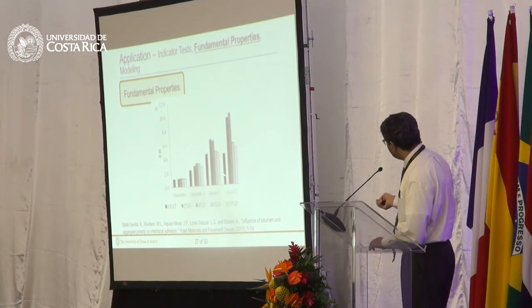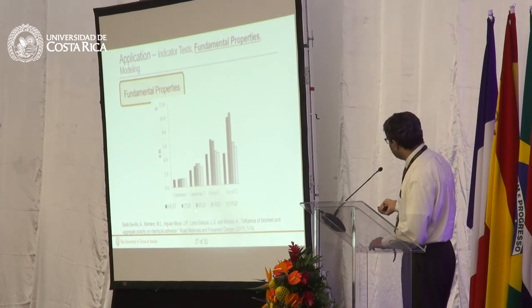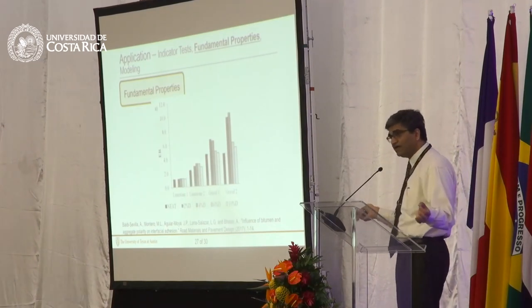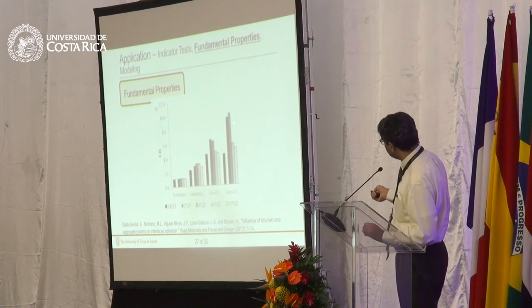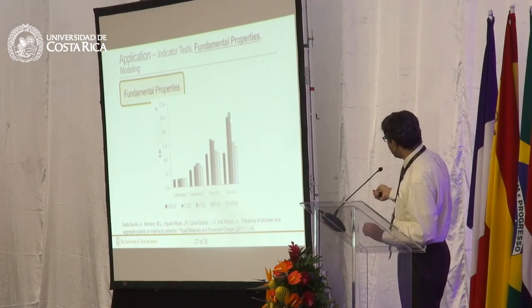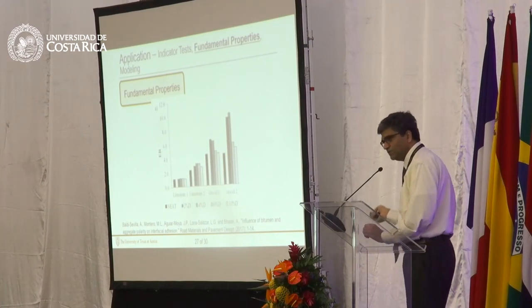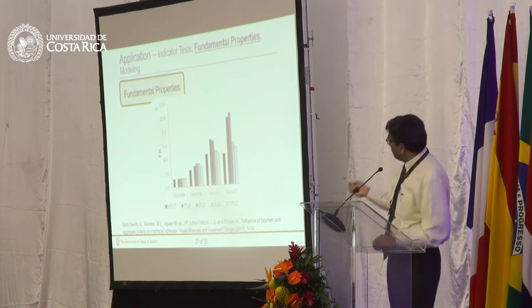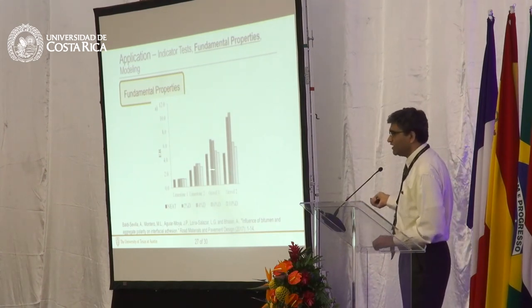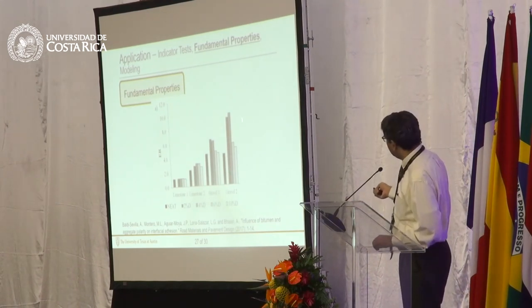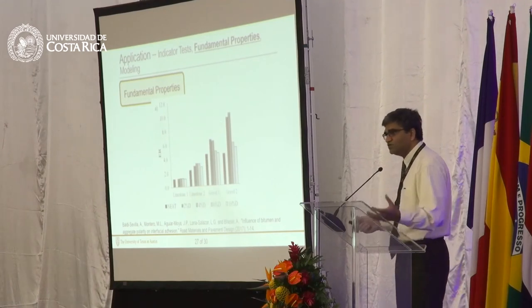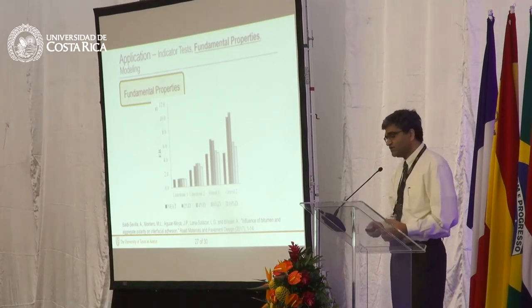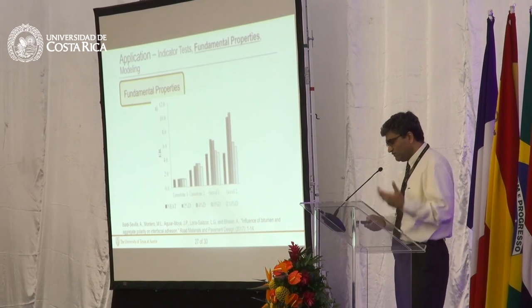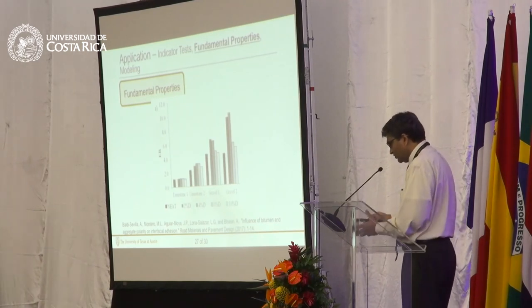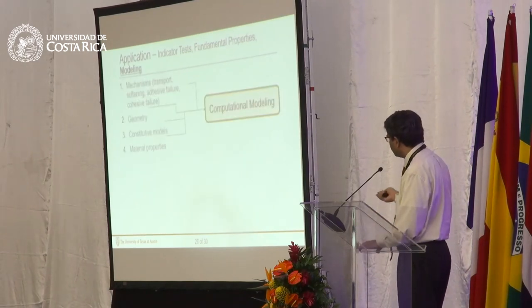She showed how using surface energy, you could get different performance with different aggregates. Not only that, these different bars within each group show different concentrations of a particular additive. So if you add a certain concentration of additive, you get best performance. You add too much of it, again, the performance dips down. This is not the end, but perhaps this is a good starting point. Perhaps you can say that in this particular case, let's try this and see using mechanical tests if this really works. So these fundamental tools give you a good guide into how you can proceed with things.